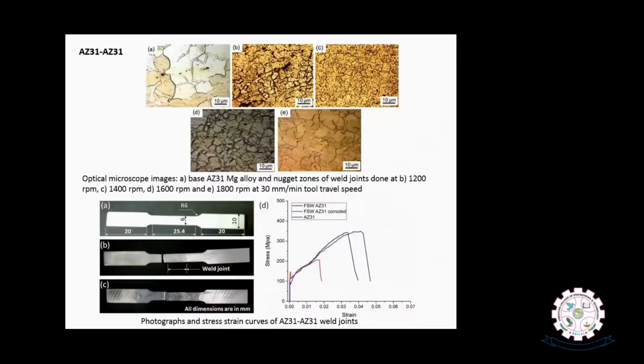Here we see a couple of joints which we developed by friction stir welding of similar and dissimilar magnesium alloys. The typical cross-sectional microstructure of similar AZ31 magnesium alloy can be seen here. With respect to the processing parameters, at all processing parameters we achieved a perfect weld joint, whereas the processing parameter, particularly tool rotation speed, has shown a significant role in altering the grain size in the weld joint.